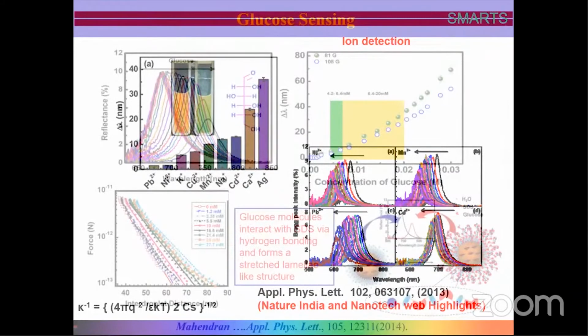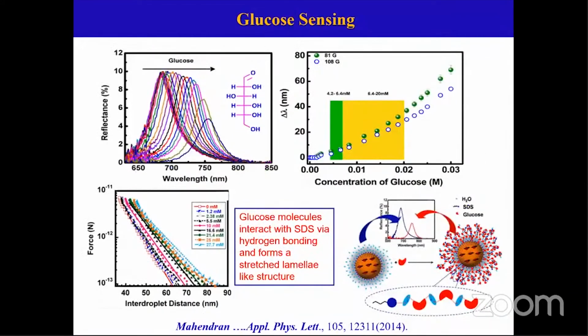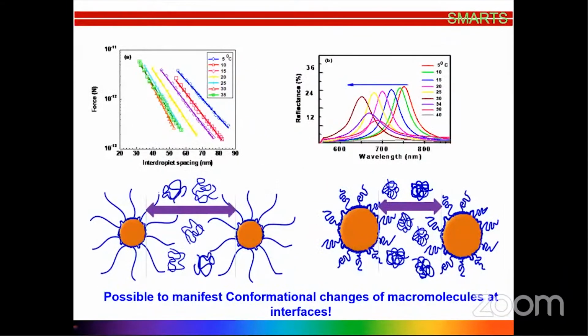And you can also, as I told you, the conformational changes that are happening at the interface of a surface can be manifested. This is already demonstrated by Israelachvili and many other groups using surface force apparatus. But surface force apparatus is a very, very difficult experiment to work with. And it takes days, and you never know when you get a good result. It's a very complicated experiment, but it's a wonderful device to probe the intermolecular forces. And no other technique can match the kind of sensitivity you can get with the surface force apparatus.